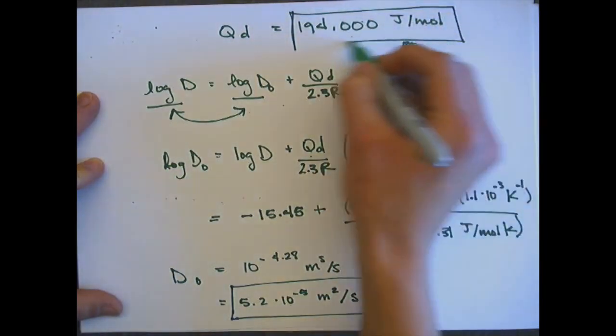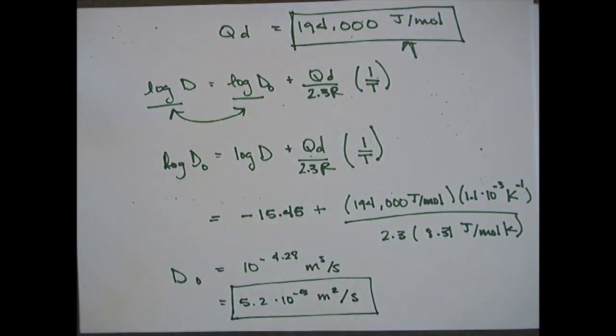So we end up with a pre-exponential of 5.2 times 10 to the negative fifth meters squared per second and an activation energy, which we already solved for. Now we have to remember that the D sub o, that was the log of the pre-exponential, so we need to do 10 raised to the power of negative 4.28, and that's how I did that last little bit there. And so now we have solved for both the pre-exponential and the activation energy.